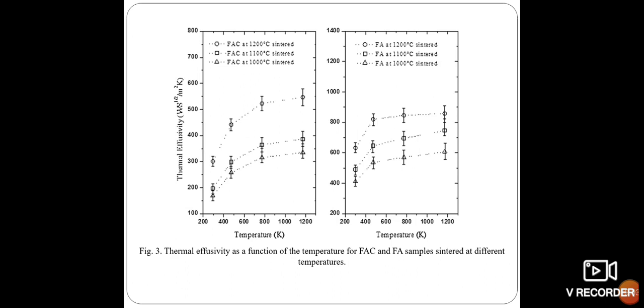It could be due to the air-filled cores in FAC samples. In this case, air has very low thermal effusivity values in comparison with the other materials. The high thermal effusivity values in FA samples mean that under transient conditions, they could extract more heat than the FAC samples.